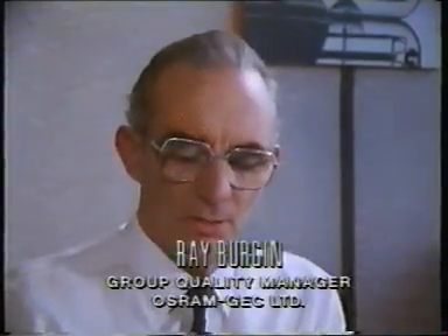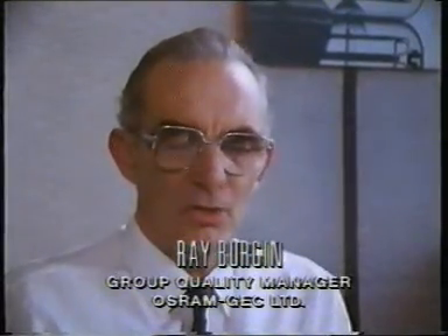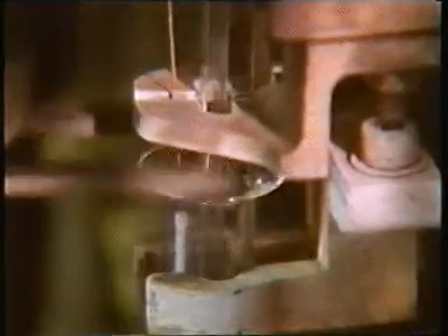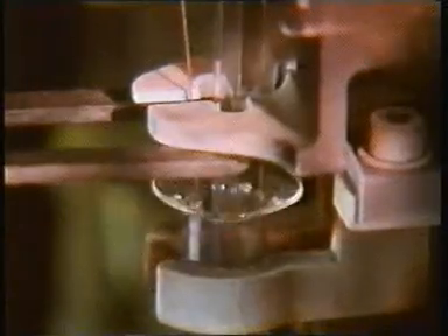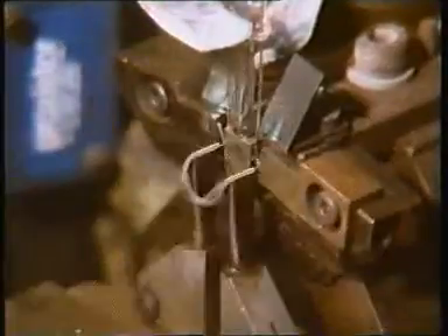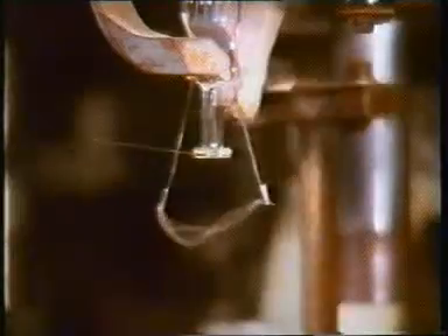The basic process for manufacturing this long interlinked grain tungsten was established a long time ago. But over the years, the process has been made much more consistent and the interlinking is better, so we have a more stable filament. This leads to benefits in manufacture. We only need to use perhaps 2 filament supports, where a few years ago we would use 3. So that's a small saving in material, and it allows our machines to run faster with those benefits.